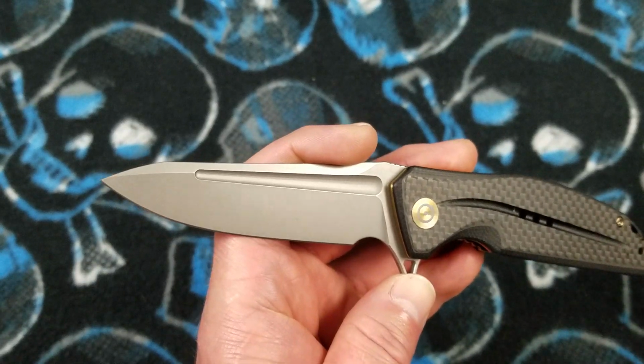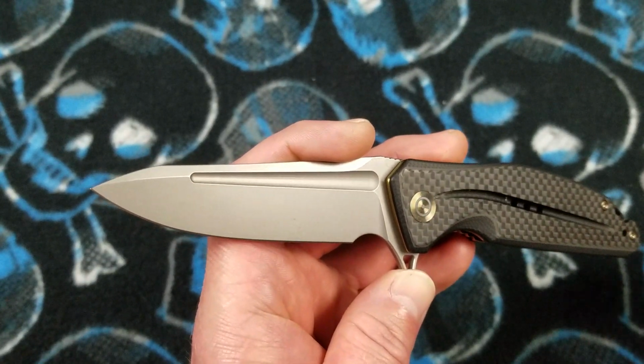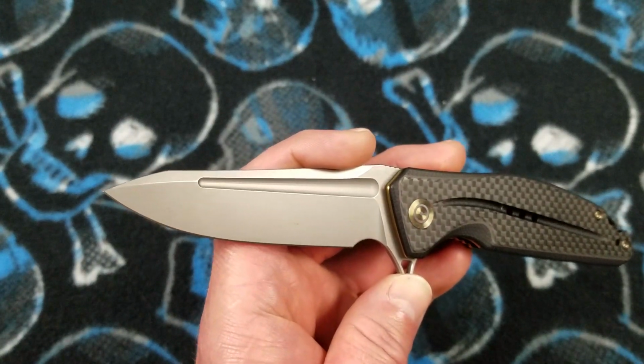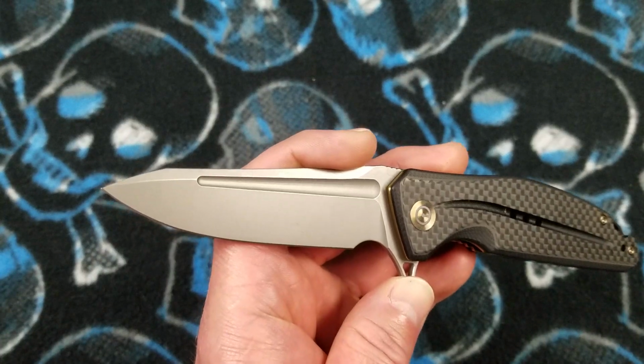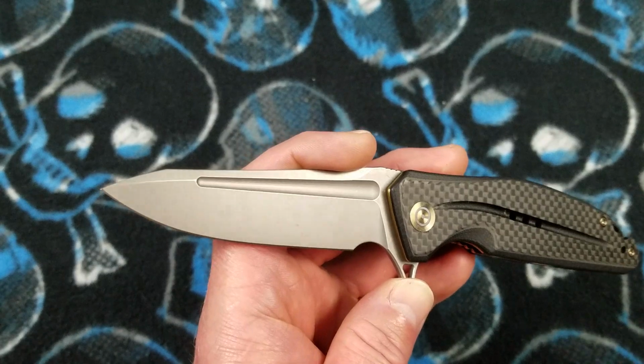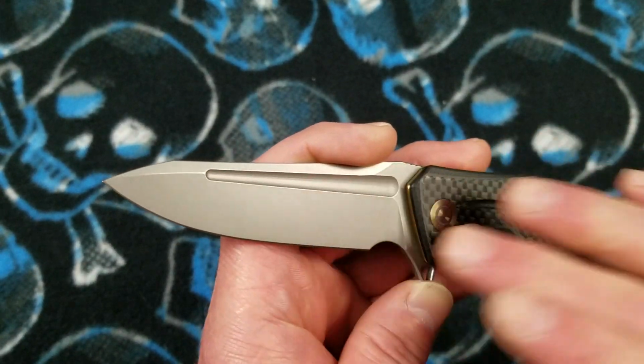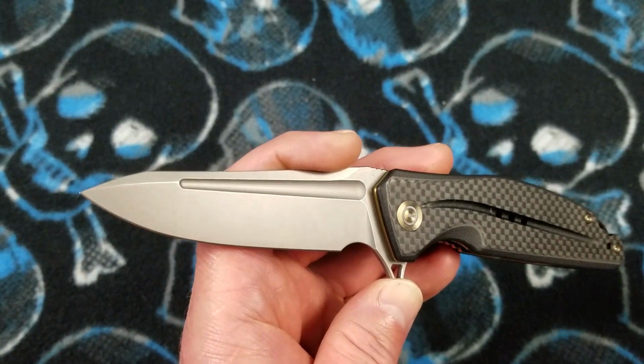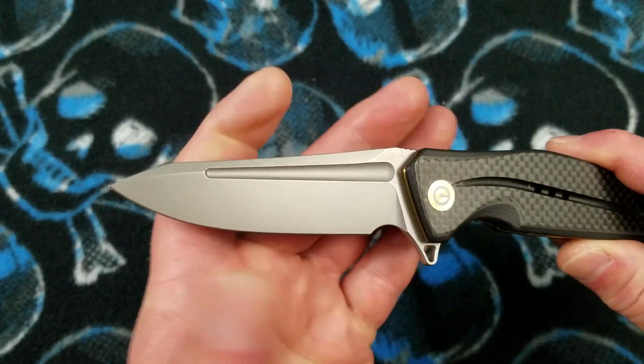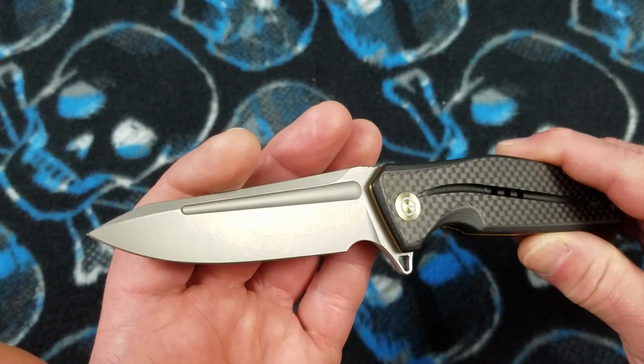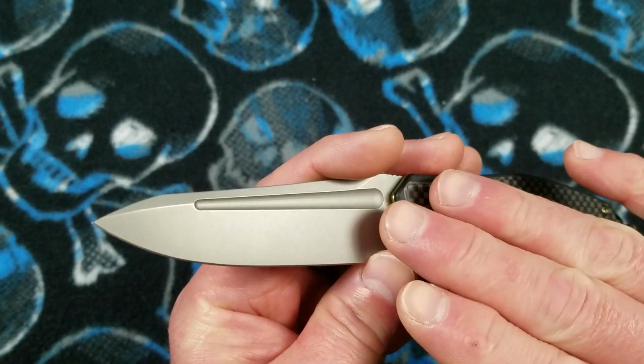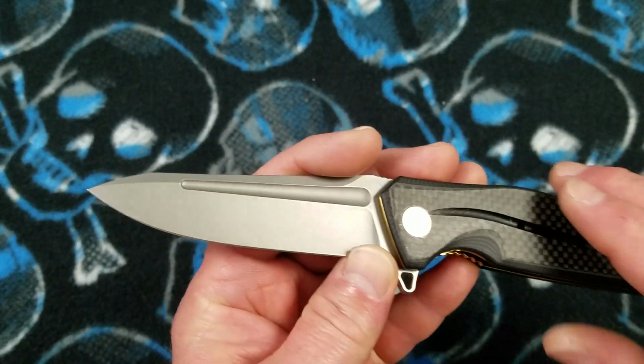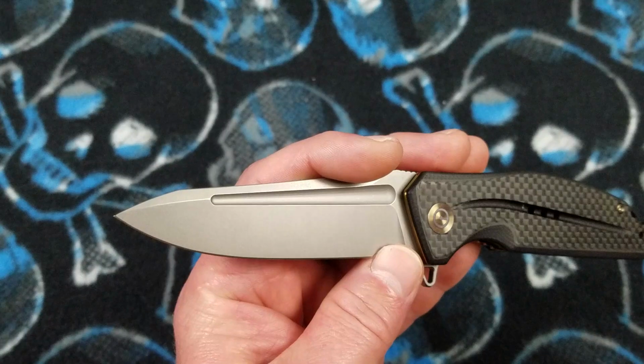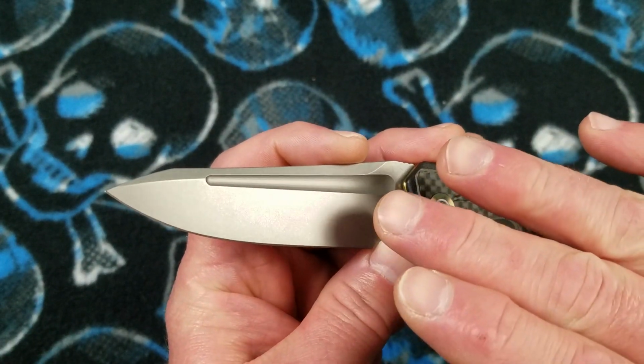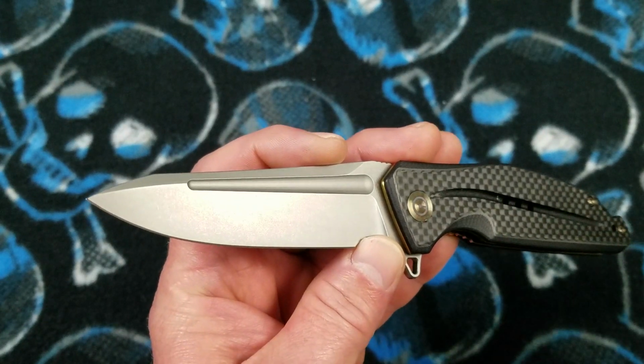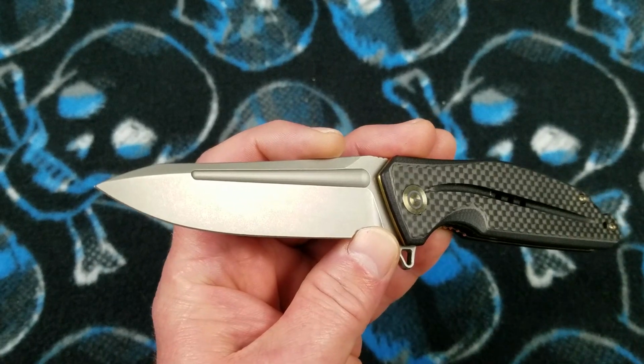You're looking at 1.5 to 1.6% carbon, 11.5 to 12% chromium. That misses the stainless qualification by a percentage and a half. It is a vanadium alloyed steel, so you get plenty of those super hard vanadium carbides suspended in the matrix of the steel because you've got a 0.9 to 1.1% vanadium content. Typically, you will see D2 run around 60 to 62 Rockwell. And with the combination of ingredients, the formula for the steel, and the Rockwell range typically gives you very good edge retention. D2 takes a very toothy, aggressive, fine edge, will hold it for a moderate amount of time, but then it really excels at a working edge.